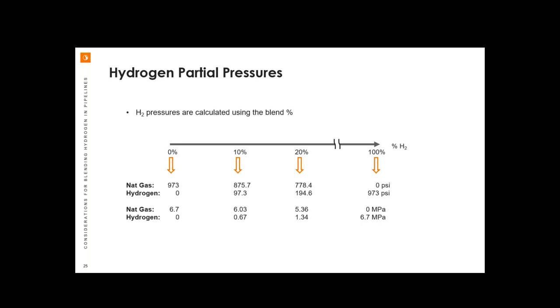We also have another important relationship, Sievert's law. That law dictates the concentration of dissolved hydrogen atoms in a solid as a function of the square root of the pressure times a constant. And for hydrogen, we find that this constant is large enough that we get an appreciable amount of hydrogen even at low pressures. So what do we need to understand? We need to understand that as we increase our mole fraction in our blend, our hydrogen partial pressure goes up. The amount of dissolved hydrogen in our microstructure is increasing. And of course, if we have more hydrogen, we have more material embrittlement.